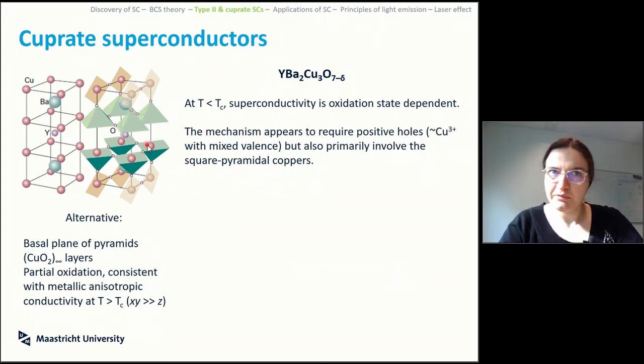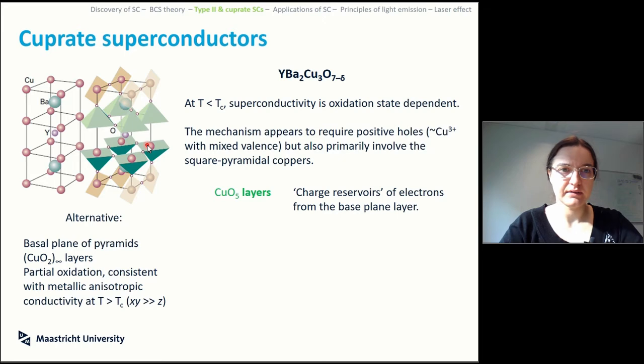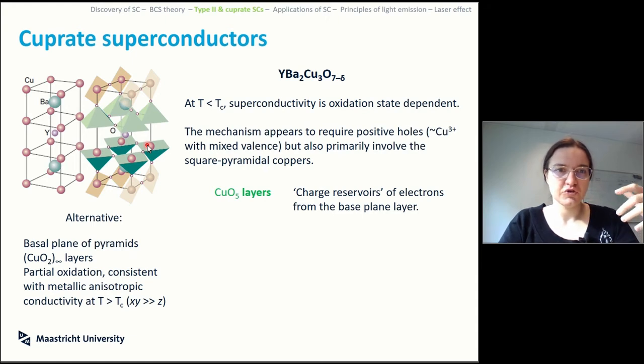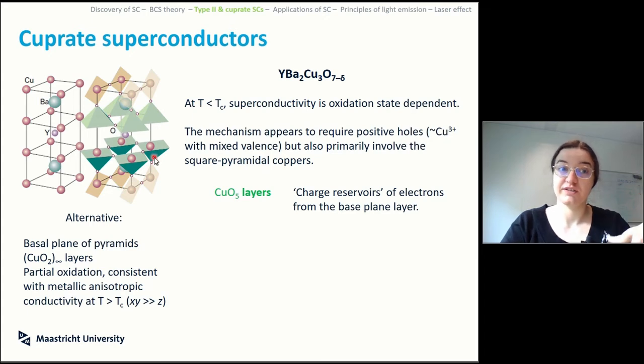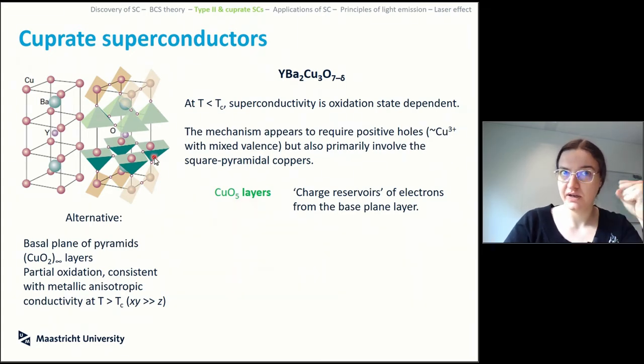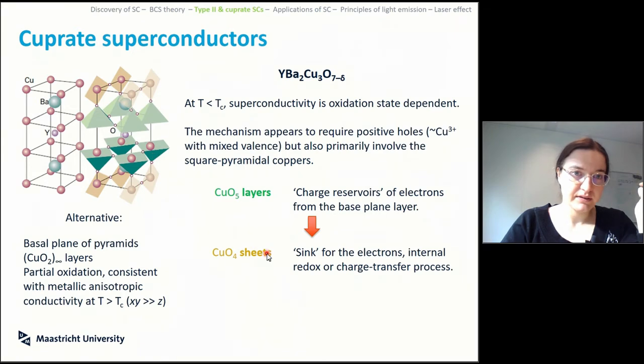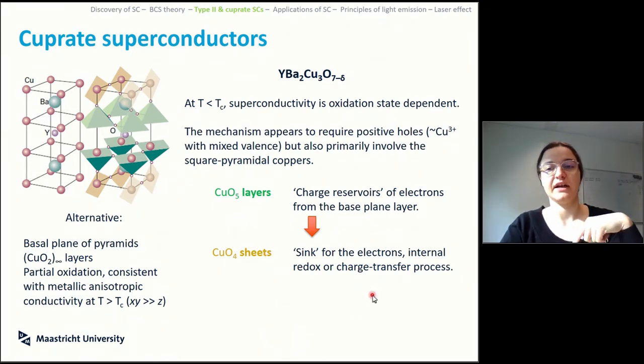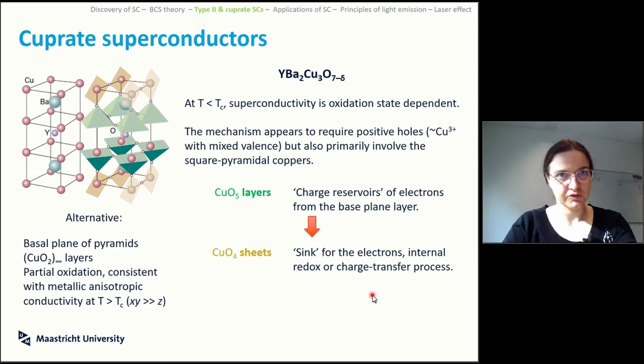So as we know, trying to make Cooper pairs here is a mess, but in this description you could basically have a superconductive state that depends also on the presence of the positive hole. So you can use the layers of your square pyramid coordination as the charge reservoir, because that's the oxidation state that will hold the additional electron. And the one that is nominally 3 plus is your electron sink, where the electrons can actually go. And there is an internal transfer of charge that can actually make your material work.